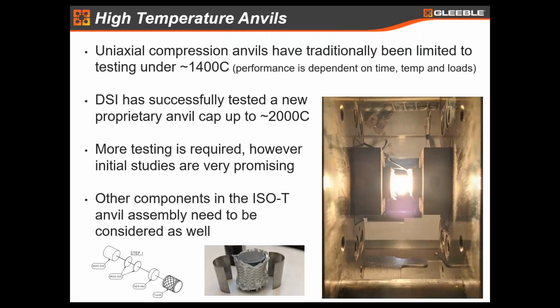All right, I want to go through quickly some new developments that we're working on as well. This one is high temperature anvils. Uniaxial compression anvils have traditionally been limited to about 1400 C. And again, that's dependent on time, temperature, loads, and the materials you're testing. But we have been testing a new proprietary anvil cap up to 2000 degrees.